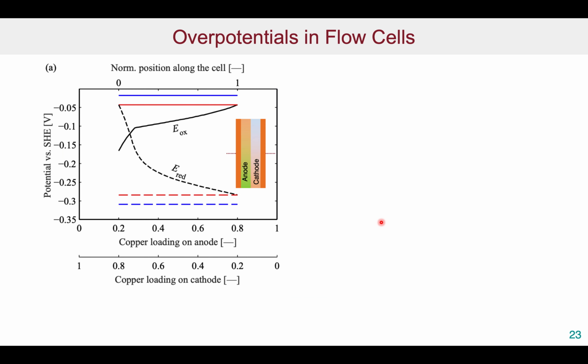So what we've got to think about is not only that, but we also have to rely on the fact that we need to drive this at a reasonable rate. So we need a stronger driving force, and this is why we have to apply overpotential, as shown in the blue here, and this provides added inefficiencies, or added energetic costs, associated with the overall process.